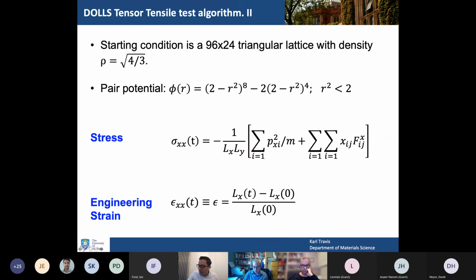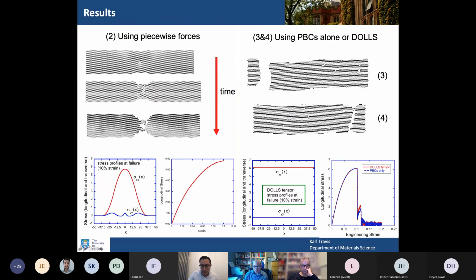Now, importantly, when we look down at the bottom, what we see is that the stress profile is uniform in both X and Y. It doesn't vary with X. The engineering stress-strain curve shows again the failure at 6, and then all this noise down here, which I cut out from the previous example, is where the material is broken apart into 2 pieces.